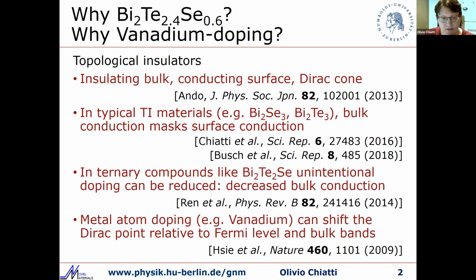One of the advantages of ternary compounds like bismuth telluride selenide is that this unintentional doping can be reduced and therefore can decrease the bulk conduction. For example, in bismuth selenide, we have selenium vacancies, which are reduced if we use bismuth telluride selenide. In bismuth telluride, we have anti-site defects, which provide unintentional doping, and this is also reduced in this ternary compound. So we have an option of reducing the bulk conduction and bringing the chemical potential into the bulk bandgap where we expect to find the topological surface states by using these ternary compounds.